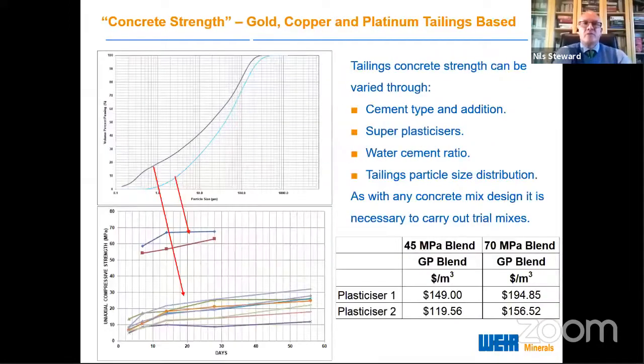In terms of copper, platinum tailings-based strengths, we've got two products. This specific one up here is a local Australian copper-based concrete, and this is a range of products that we manufactured from platinum tailings. And we're able to vary the strength in exactly the same way as you do with typical cement technology: cement type, the rate of addition, and the superplasticizers used.